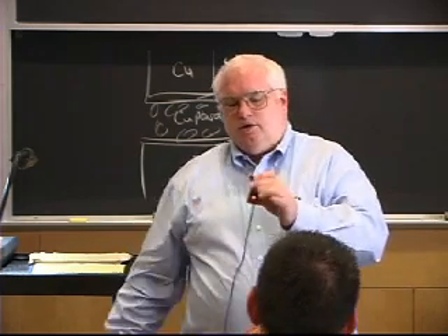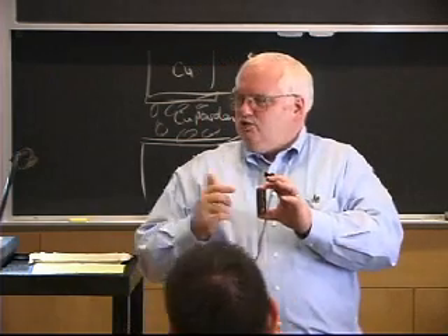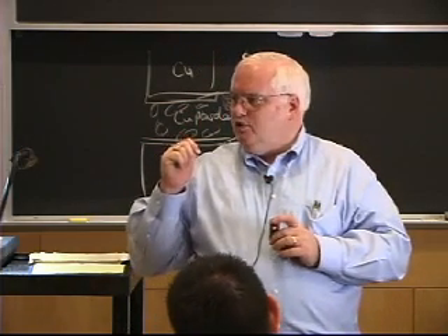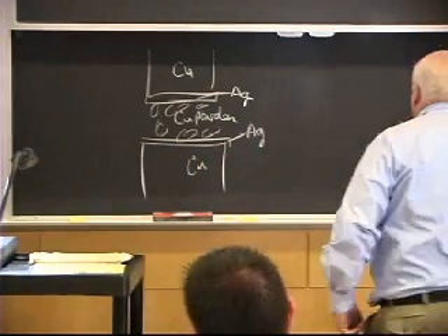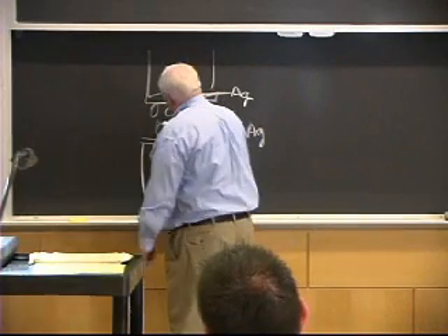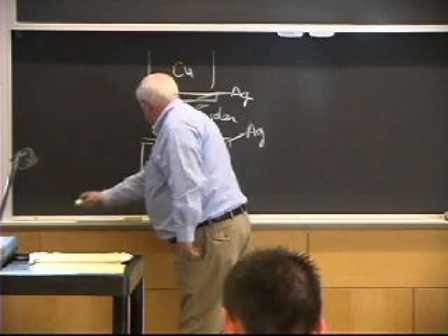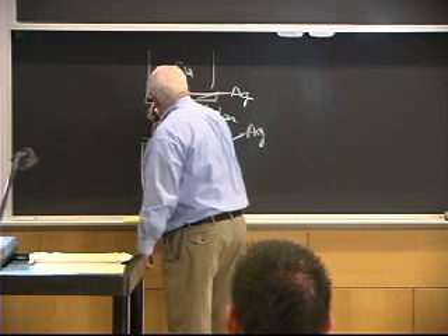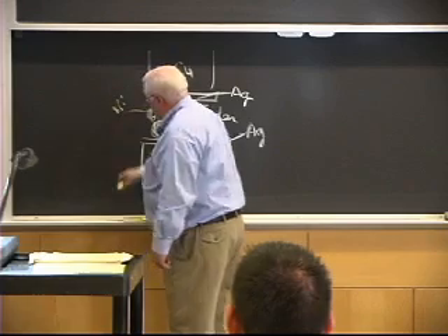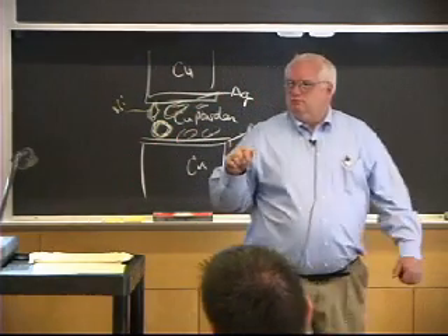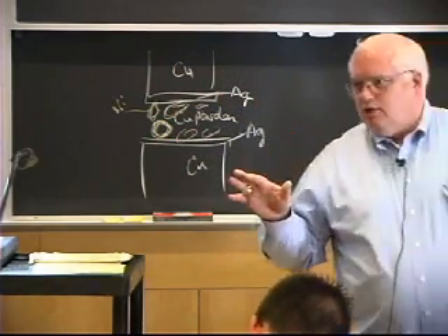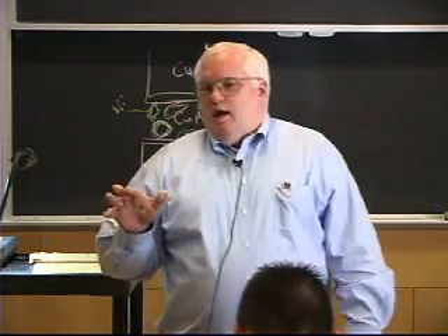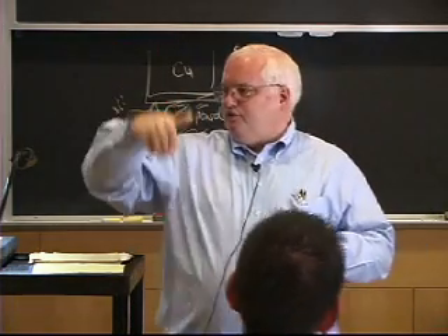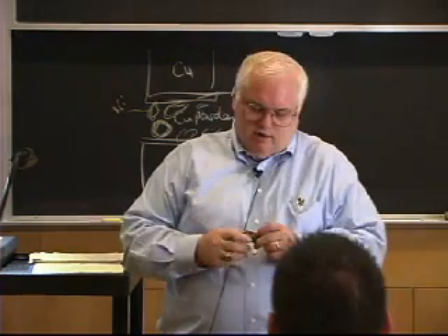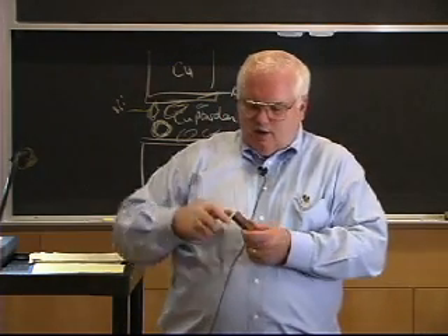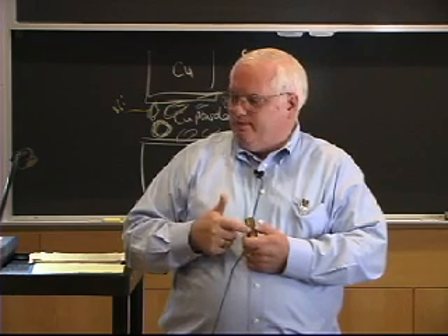But this one actually is well over a centimeter thick, and what we did is we took the copper powders and we plated them with nickel. And nickel will not dissolve silver. Nickel and silver are immiscible in both the liquid and solid state. And so now I have silver infiltrating nickel, which it doesn't erode, it doesn't alloy with. And because of that, I can get very deep infiltration of the silver.